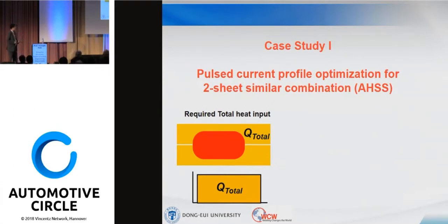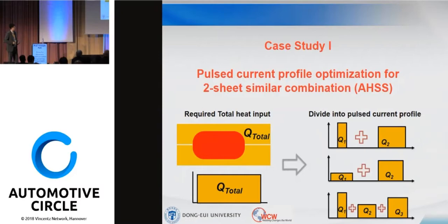Here's my case study. Pulsed current profile optimization for two-sheet similar combination, especially for advanced high-strength steel. Well, with any combination, I can calculate, or anyway measure, the required total heat input for the welding. However, if I want to use the pulsed current profile, here's my headache. How can we divide it into the pulsed current profile? Should we divide this total heat input into 2 heat inputs or 3 heat inputs?